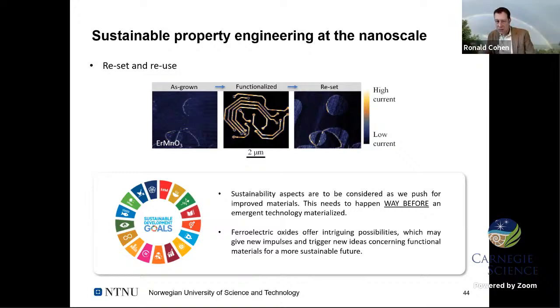That's a bigger problem with the proper ferroelectrics. There, people usually use the domain walls, they create them and erase them in between electrodes to control conductance. So there you don't want them too stable, so you can write and erase them. Here we want them to be stable, because with the point defects, it's the same with the anti-Frenkel. Since they are charge neutral and screened, they can last on much longer time scales than just the charge defect, which will somehow interact with the environment.